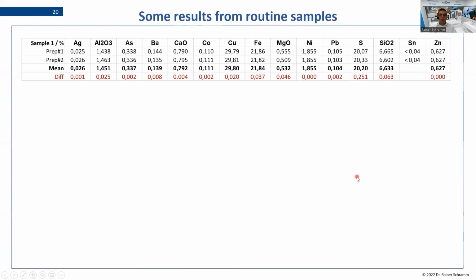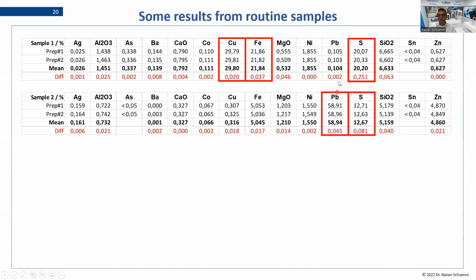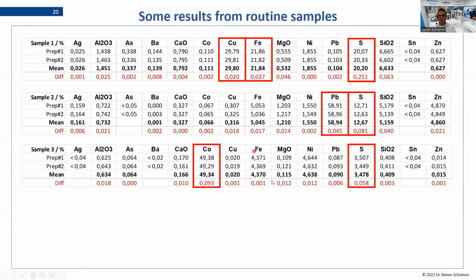Some results. So if we just prepare from a copper ore two glasses from the same ore, you see a fantastic precision. So the reproducibility of the two preparations is really perfect. Same we could say for the lead ore, or the same we could say for the cobalt ore. So you see that for the sulfur, like I told you already, there's some risk always that you lose it. Here you will see a higher error, but for the element of interest, the main component, and of course also the side components, even the silver here, you can really do a good accurate analysis here.